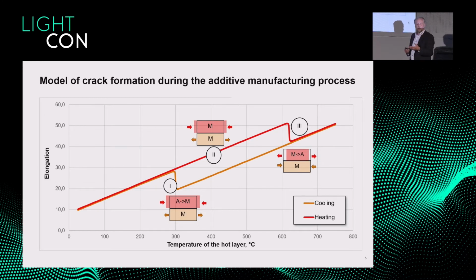If you have a hard phase like martensite, the stress increases and you produce cracks. At the very high temperature, you have a reverse transformation from the low temperature phase to the high temperature phase, and this causes also internal stresses, but you are in the high temperature range, that means the material is rather soft, and you also produce additional austenite, it's also soft, so the risk of cracks in this case is rather low. So what are the right materials?